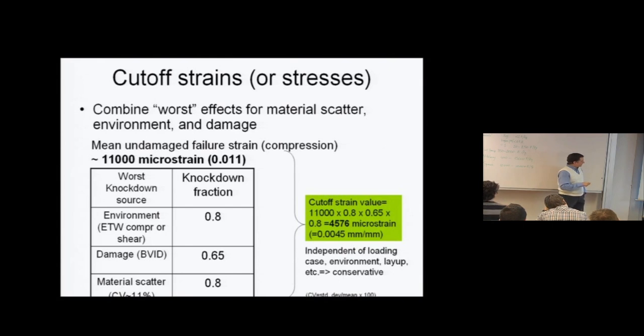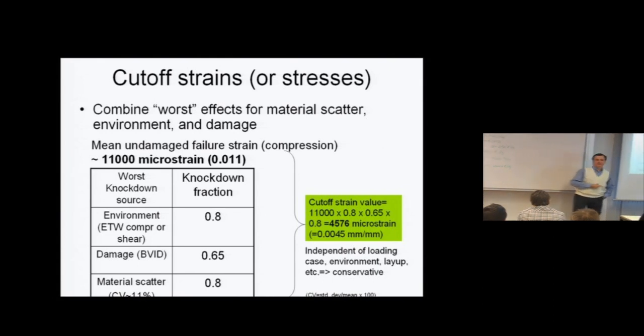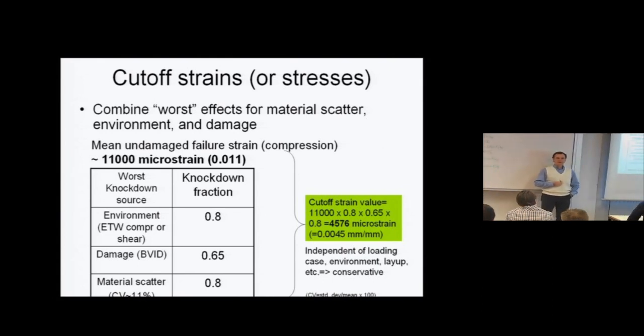So if you take all these three together and you multiply by this 0.011, you will find 4,576 microstrain. And if you go and look at ever since the 70s, the typical cutoff strain values being used in composites were 4,500 microstrain. So there is a reason which is very much strongly related to this.